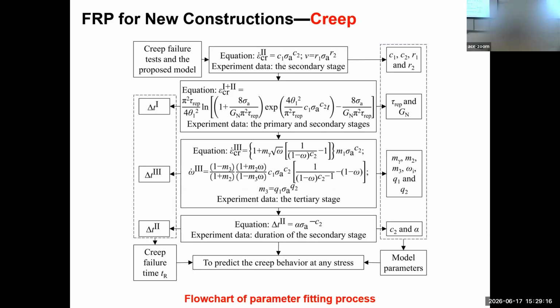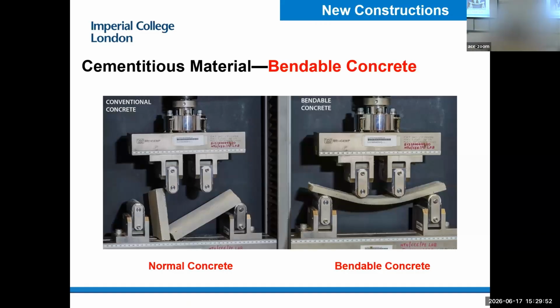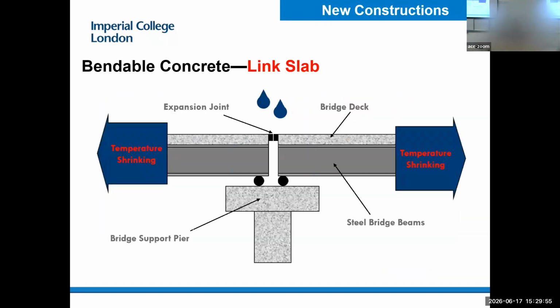It looks very complex. However, you can use coding to make it a coding package. You don't have to do the calculation manually. You just need to do a very simple sample creep testing, then input the testing results in the coding package, and it will work out the material constants. Then you can use that model to predict the creep behavior of the material at any stress. I also did some research on ECC, but I don't have time to go through it.